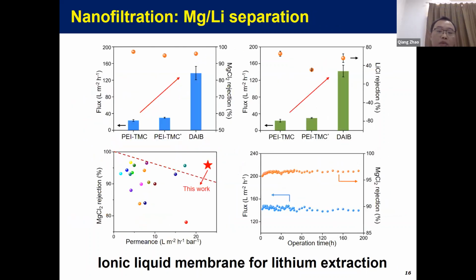With this in hand, we went further to design more ionic monomers, especially for lithium and magnesium separation. Here is one example. We designed a DAIB monomer to modify the PEI membrane, and we found that the flux was improved by almost 4 times, while the selectivity was maintained.